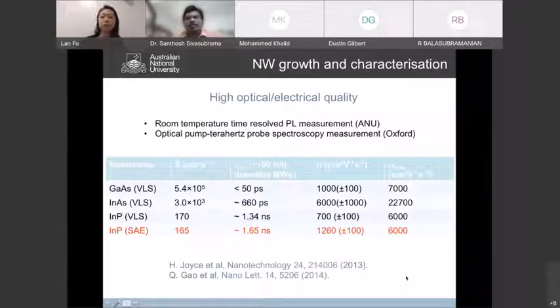If you look at the optical and electrical properties, we can see that our SAE-grown nanowires have very low surface recombination velocity, which is a very important property for a lot of optoelectronic applications. It means that you don't have a lot of recombination at the nanowire surface, which is always a concern for nanowire devices because of the large surface area. And then we have good carrier lifetime, which is again another indication of important optoelectronic properties. Mobility is also very good compared to a lot of VLS-grown material. So all this gives us a very good starting point to make them into optoelectronic devices.